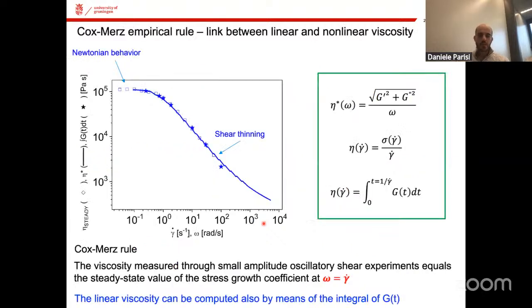Conveniently, there is another thing that we can get from the rheometer. I'm sure that you have heard about flow curves, or if you want, how the viscosity changes as a function of the deformation rate of a system. So most of the polymers are so-called shear thinning. It means that for very low deformation rate, the viscosity doesn't change, so you have a sort of Newtonian behavior. But then if you start increasing the deformation rate, the viscosity decreases, and this is known as shear thinning behavior. And this is actually the reason why we are able to process polymers, especially polymer melts, because the more you deform, the lower the viscosity becomes.